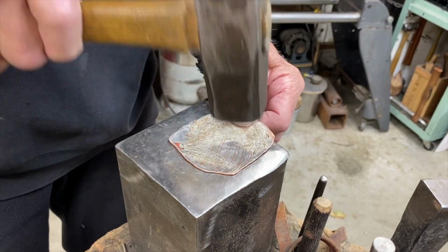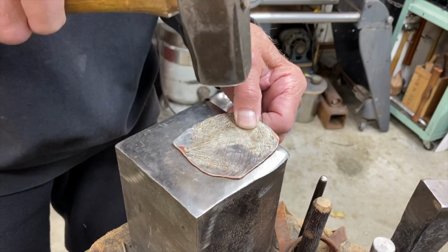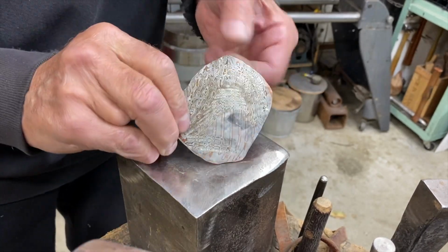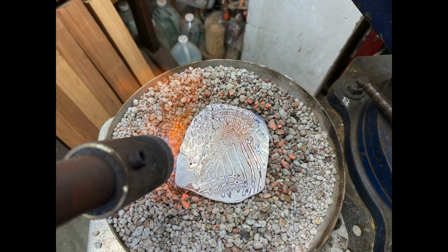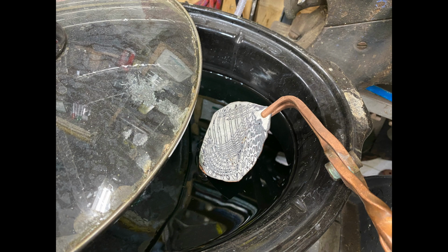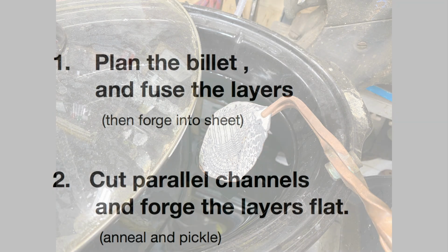Again, we gently forge the channels flat with the rounded hammer. We lightly flatten the result, and then anneal it. And last, we pickle. Let's patina this sample in Rokusho for an hour or so. Meantime, this is what we did.